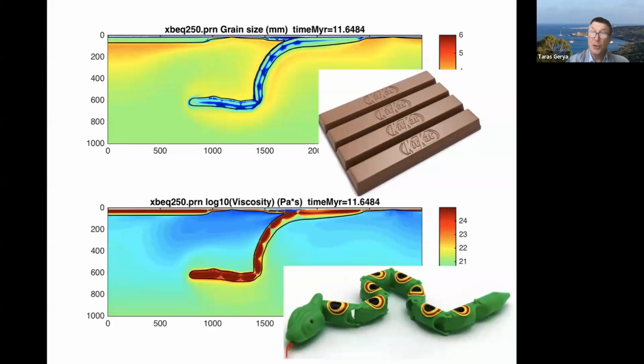So the slab is not weakened equally everywhere. Instead, there are segment boundaries which are very weak, and there are also segments themselves which remain rigid. The flexibility of the slab and its easiness in deformation is essentially given by the alternation of these weak and strong slab regions. And again, I'm repeating, these should continue along the length of the slab. The model is two-dimensional, very obviously, but it implies that in the third dimension we should have some uniformity in the position of these segments along the trench.